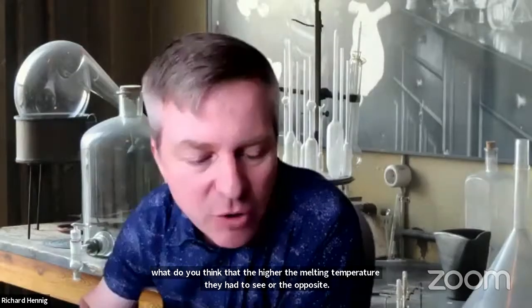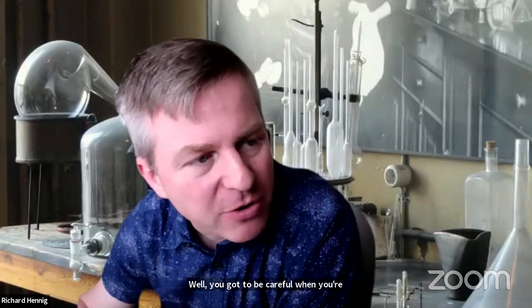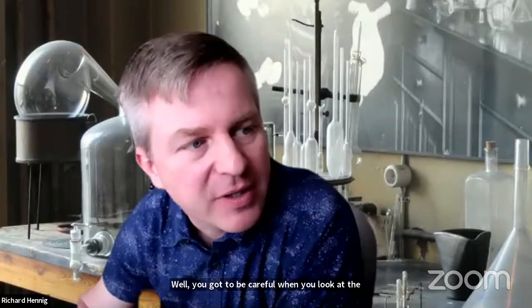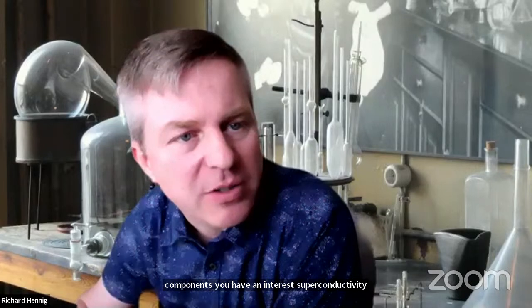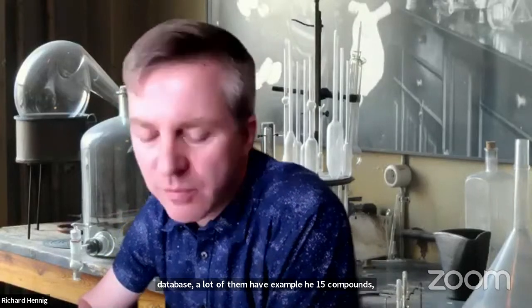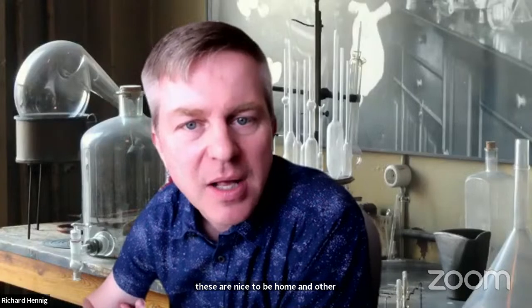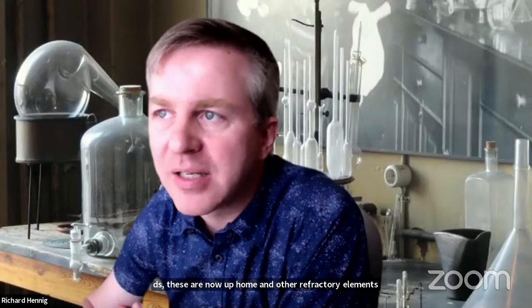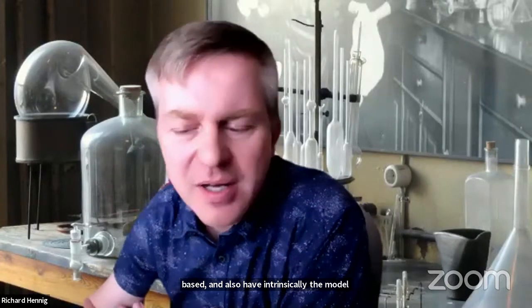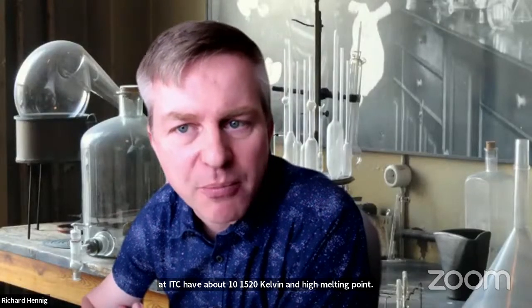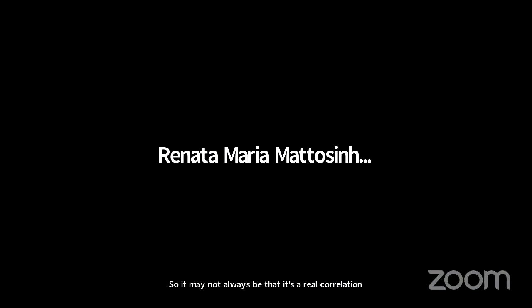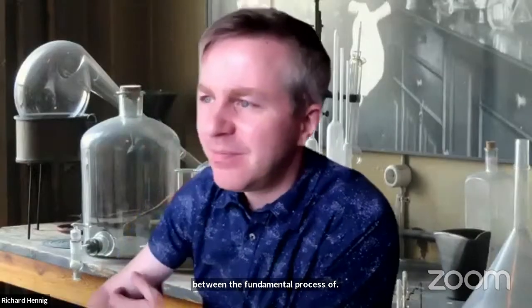Yeah. So would you think that the higher the melting temperature, the higher the TC, or the opposite? Well, you've got to also be careful when you look at the compounds you have in those superconductivity databases. A lot of them are, for example, A15 compounds. These are niobium and other refractory elements based. And those have intrinsically a moderately high TC of about 15, 20 Kelvin and a high melting point. So it may not always be a real correlation with the fundamental process of superconductivity, but more data bias to some extent.